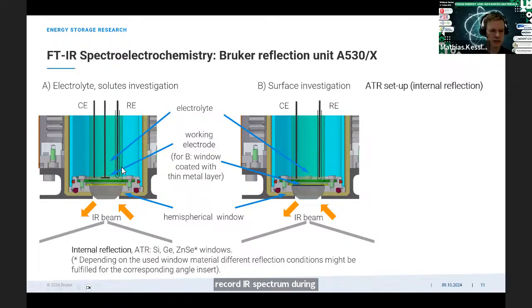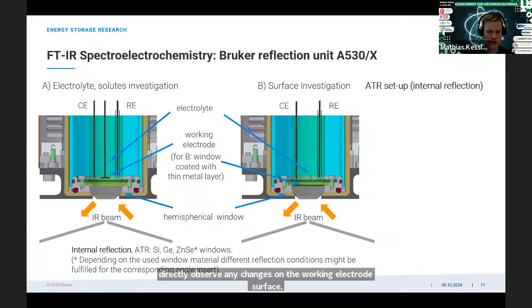And we have the possibility to either measure only the electrolyte, then we place our three electrodes simply inside of the electrochemical cell, or we do surface investigations, and for that we can coat our ATR crystal with a thin metal layer, which is made of gold usually or platinum. And then this metal layer is connected electrically and works as working electrode. And with that, we have a surface sensitive setup and directly observe any changes on the working electrode surface. And this is very often used because these processes, the electrode processes, are the most important ones.